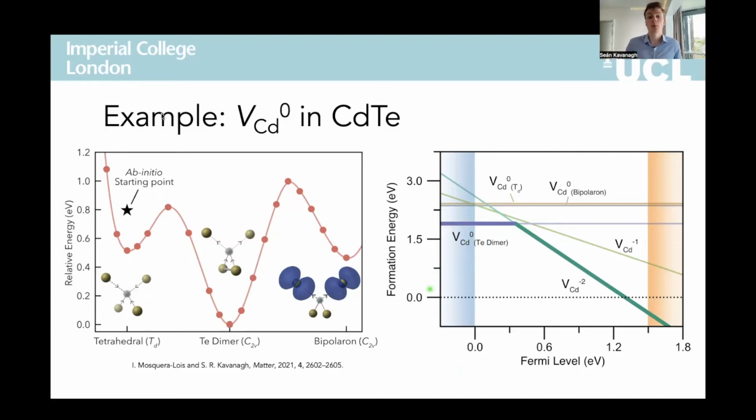By negative U, we mean a double acceptor level where the equilibrium charge state jumps directly from neutral to -2, and so the singly charged -1 state is always unfavorable and would rather disproportionate into neutral and -2.